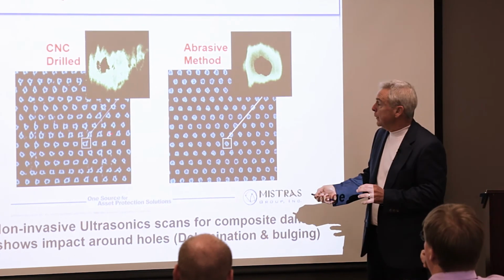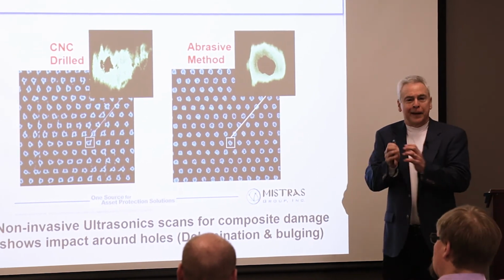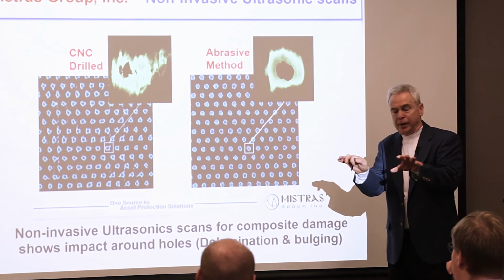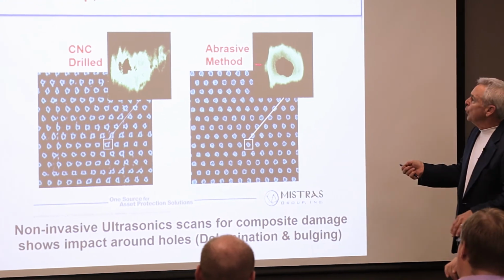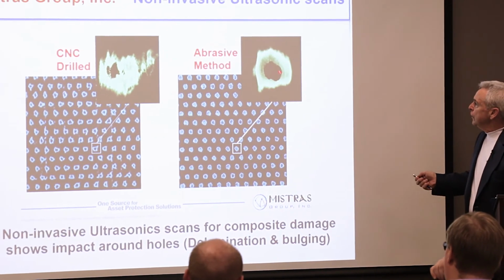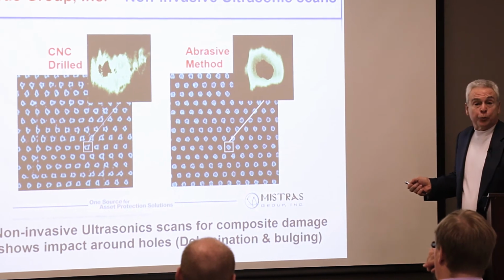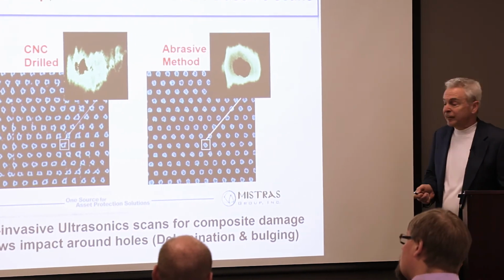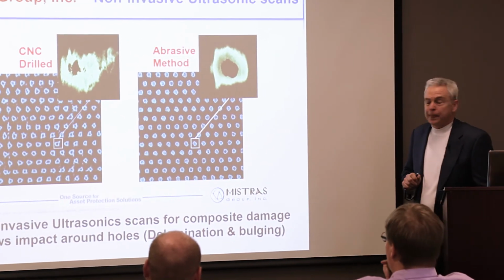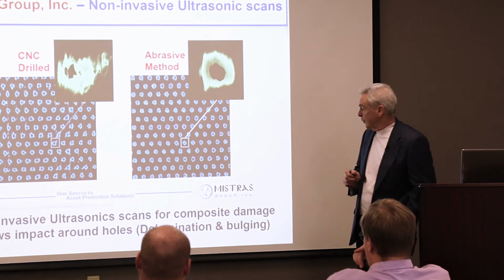If these holes are much closer together, that can really be a problem and cause these composites to come apart. However, with the abrasive machining method, you can see that it's much more uniform, the stresses are much less, and the damage is much less. So that's a real plus.